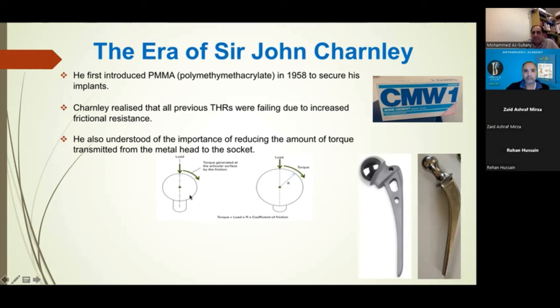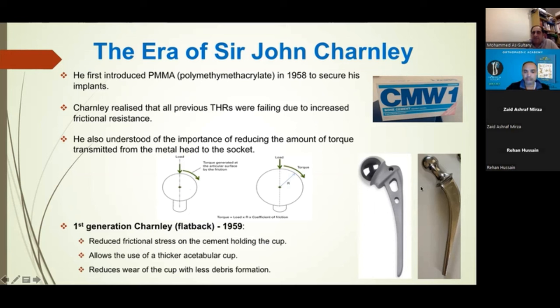So you can see here the concept of trying to reduce the amount of torque, and you can compare Charnley's first generation stem, called the flatback, 1959. The size of the Austin Moore head, he started off with a 42 millimeter head, and then he gradually reduced the head size to 28, 25, and then ended up at 22.225 as the most ideal head size. Because any smaller than that, then you risk dislocation. So the risk of dislocation after that would substantially go up. So he felt that was the optimum head size to reduce the amount of torque, but also not risk increasing the risk of dislocation.